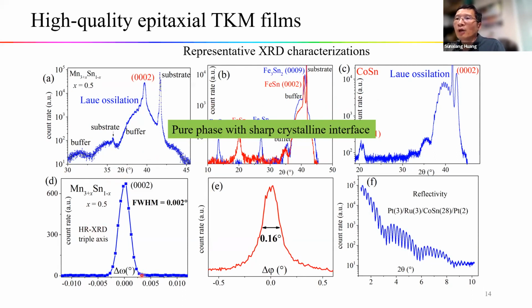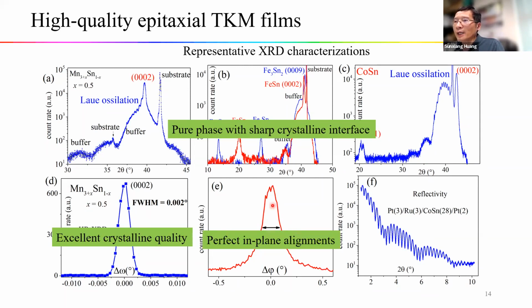The rocking curve, the omega scan with the triple axis analyzer, shows the peak is extremely narrow with a width around 0.002 degrees, which is roughly close to the instrument limit. So this indicates the kagome plane is perfectly parallel with the film plane. The in-plane phi scan is also very narrow, which indicates the in-plane alignment between different grains is almost perfect.